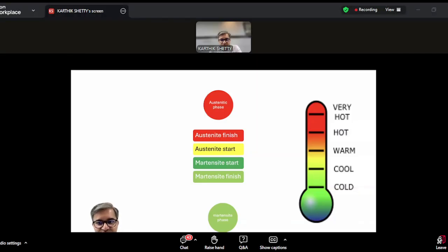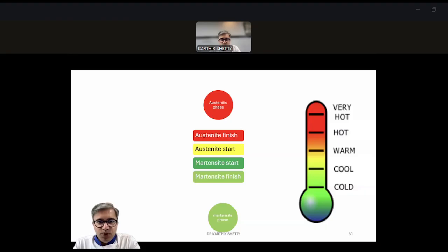All right. The last slide again tells you, at higher temperatures we are austenitic, at lower temperatures we are martensitic. And it need not be fully austenitic or fully martensitic. We may want a little bit of stiffness, a little bit of flexibility, more stiffness, less flexibility, or more flexibility, less stiffness. This has been done by the manufacturer for you. So the manufacturer has put in four program temperatures into your files. At the highest temperature, it will be fully austenitic, that is beyond austenitic finish, AF. When the temperature reduces, it will reach a point where it will be austenitic start, and beyond that, as you go lower, the martensitic phase will start.